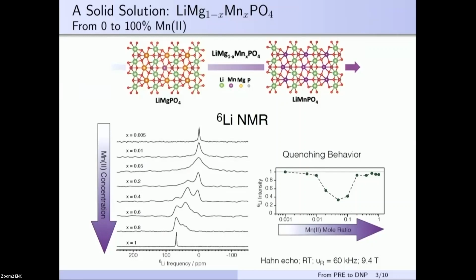What this figure is telling us is that the increase in paramagnetic content must be affecting properties of the electronic spins. As we have more and more manganese, the electron couplings become stronger, and this will cause the electron relaxation times to change. Ideally, we would like to probe this, and the best way would be to do EPR measurements. But measuring electron relaxation times with EPR at these high concentrations, at fields and temperatures of interest, is extremely challenging or even impossible.